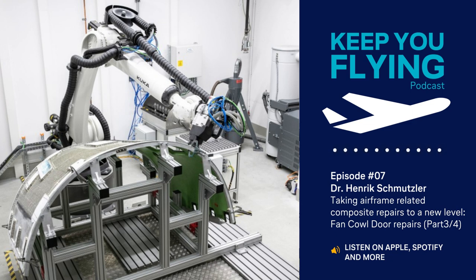The deviation of the different areas not to machine can easily reach magnitudes that go far beyond the required accuracy and strongly affect the reproducibility of the automated process for supposedly identical parts. Additional deformation can occur during the actual milling process while the plies and honeycomb material that compensated thermal stresses during manufacturing are removed. The resulting deformations also surpassed the required accuracies and therefore had to be carefully taken into account when we developed and industrialized the robotic process. As already described for radomes, balancing the geometric variance of a part versus the required support for its machining process is also important for the Fan Cowl Doors.